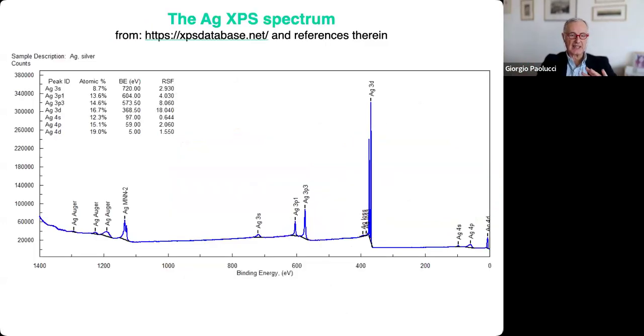In XPS, a photoelectron spectrum looks like that. You can find it at this website, which is a public one. So you can go there. This is a silver sample, excited with a standard laboratory source. In this case, it's aluminum K alpha, so it's a bit more than 1.4 keV. Indeed, as you can see, the maximum binding energy is 1.4 keV.